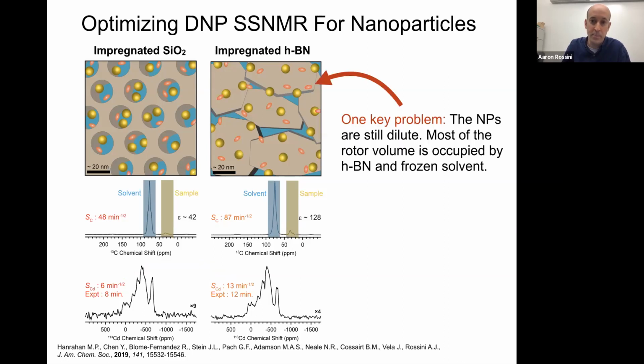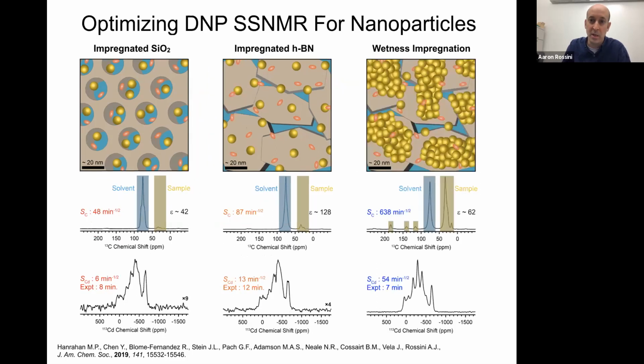So that's pretty good. One problem though, if you look at this cartoon, it highlights what the issue is. We're interested in studying the nanoparticles, and most of our rotor volume is going to be occupied by solvent and the boron nitride that we're using to disperse the nanoparticles. The way we can get around this is we can precipitate our nanoparticles as powdered aggregates. We can then mechanically mix it with the hexagonal boron nitride, or alternatively, you can just take your nanoparticle solution, put it onto the hexagonal boron nitride, let the organic solvent evaporate off, then you can impregnate it with a small volume of the TEKPol TCE solution.